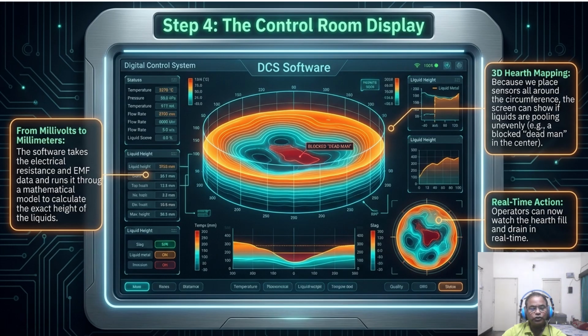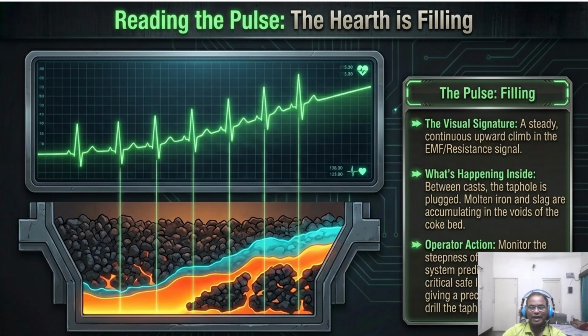So to use this effectively, you need to recognize the three distinct pulses of the tapping cycle, which are very important. As the slide is showing, between casts, when the tap hole is plugged, we see the pulse filling. Notice the steady continuous upward climb in the signal. Inside the furnace, molten iron and slag are accumulating in the voids of the coke bed. As an operator, your job is to monitor the steepness of this climb. So the system uses this to predict exactly when the critical safe limit, usually 50% occupancy, will be reached, giving you a precise countdown to drill the tap hole.